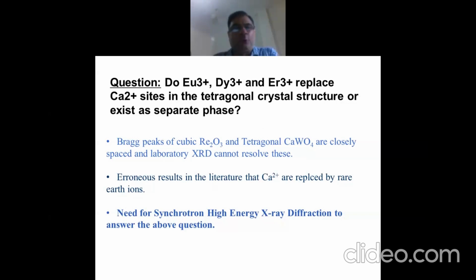There are in fact erroneous results in the literature that the calcium ions are replaced by the rare earth ions. These conclusions were derived from low resolution X-ray or neutron diffraction measurements. So there is a need for synchrotron high energy X-ray diffraction experiments to answer the question. We did these experiments at our third generation synchrotron, Indus 2, at Raja Ramanna Centre for Advanced Technology, RRCAT, at Indore.